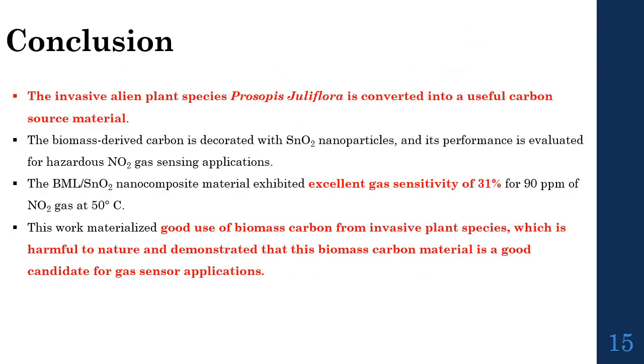As a conclusion, the invasive alien plant species Prosopis Juliflora is converted into a useful carbon source material. We decorated SnO2 nanoparticles on the biomass and evaluated its response for hazardous NO2 gas sensing, showing excellent gas sensitivity of 31% for 90 ppm of NO2 gas at 50 degrees Celsius. Overall, this work demonstrates good use of biomass carbon from an invasive plant species harmful to nature, and shows that this biomass carbon material is a good candidate for gas sensor applications.